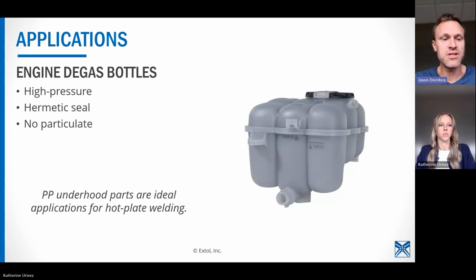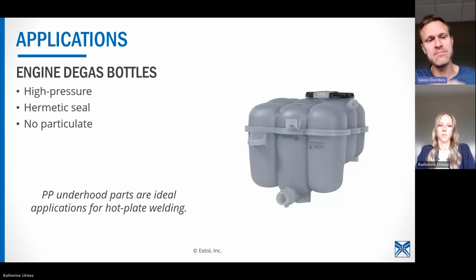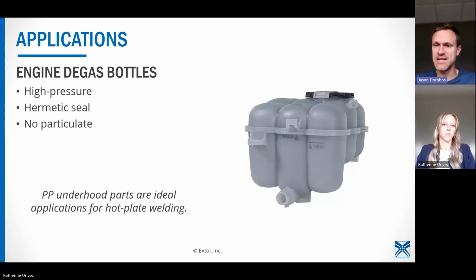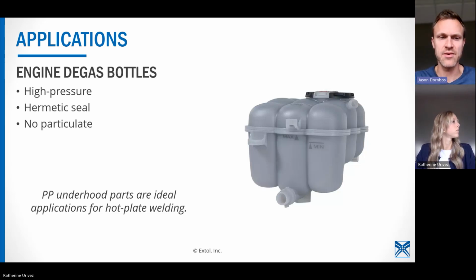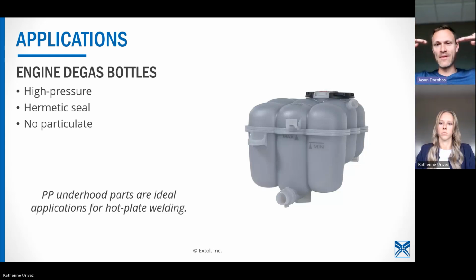One of them is in engine degas bottles. These have internal walls that are being welded, and this part is pretty stout. These need to be very strong. But because of the geometry of it and the material that's used to make it, there's big amounts of sink that show up on the weld surface. Again, this is an area where if you're not hot plate welding this, it would be difficult to get a good consistent strength and good consistent leak proofness, because the weld surface is supposed to be flat, and there's big areas where it dips way down because the part has shrunk after molding, and in some of the thicker areas it shrinks more than others. And so because we're planing that off and making sure it's totally flat before we weld them together, we get good strength with hot plate welding.